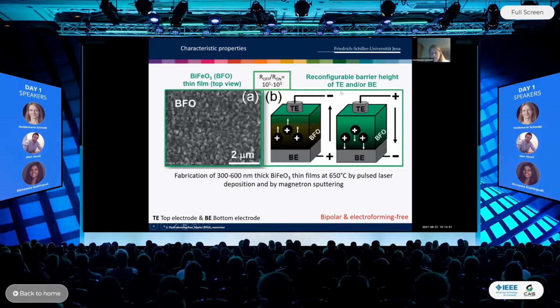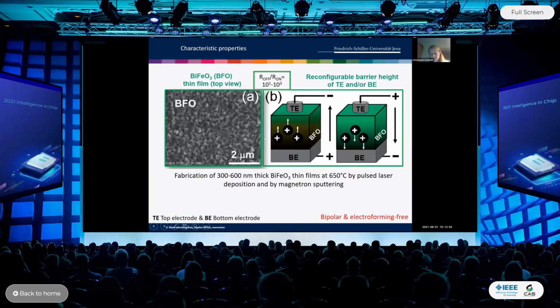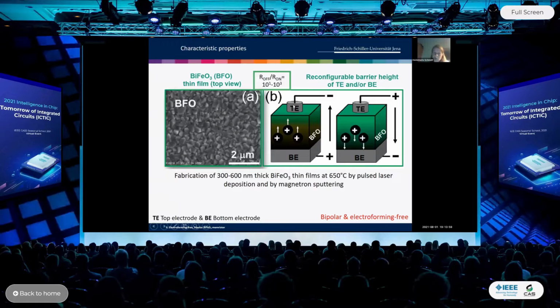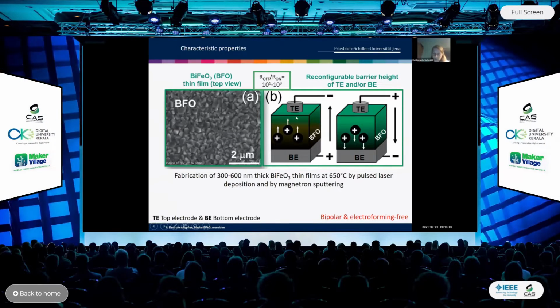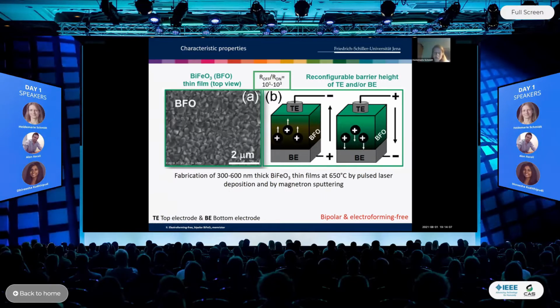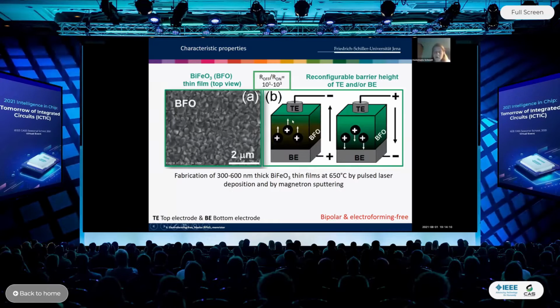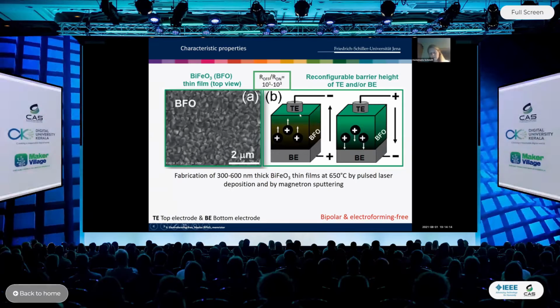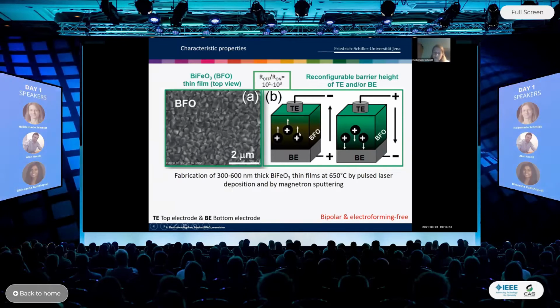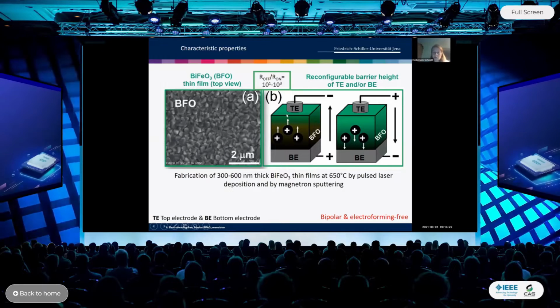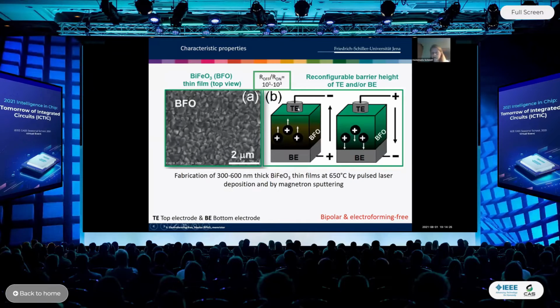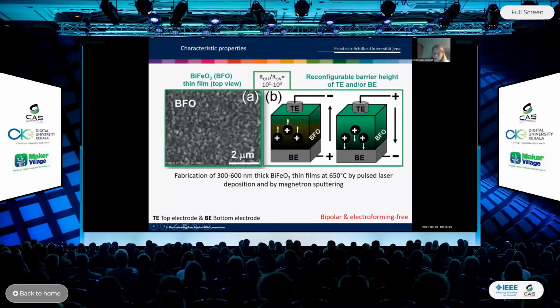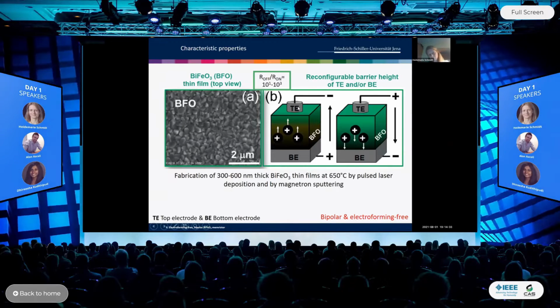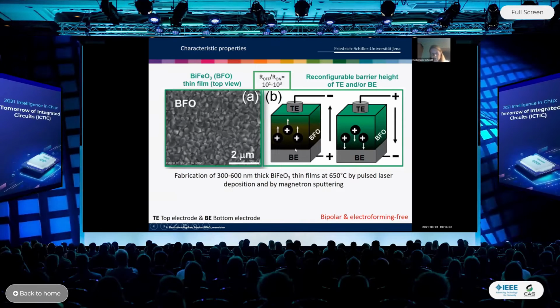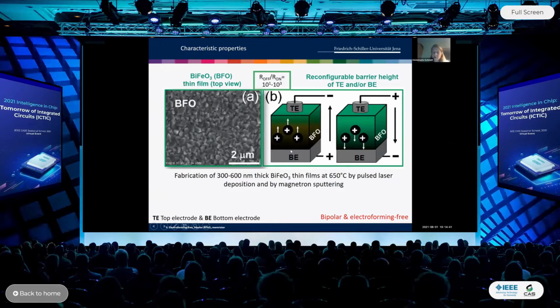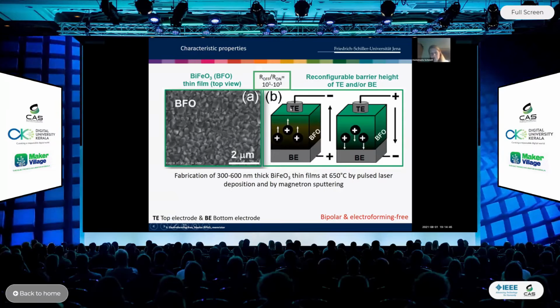However, if we apply a negative bias to the top electrode, the positively charged oxygen vacancies will drift towards the top electrode. And if there are traps available, which are the titanium ions incorporated in the bismuth iron oxide lattice, they will capture the oxygen vacancies at the position of the top electrode. That means oxygen vacancies are at the same time donors. And we have a very large concentration of donors close to the top electrode. That means the barrier height of the top electrode is reduced because we have a large concentration of donors there. Okay, that means the top electrode is ohmic, non-rectifying, and the bottom electrode, because there are nearly no oxygen vacancies left, is rectifying. So we have a Schottky diode, which is reverse biased.